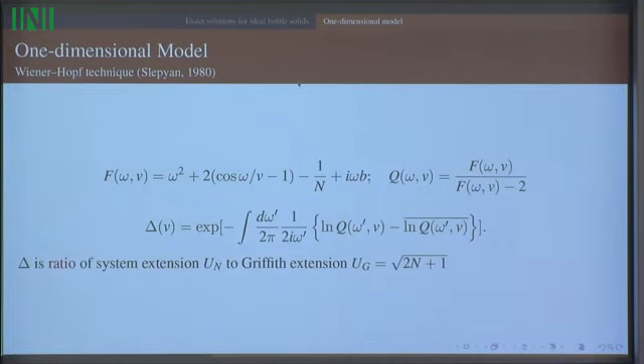So I measure extensions in units of that, and if I do that, then if I stick in a crack velocity v here and then just do an integral over this dummy variable omega prime, then I obtain how hard I have to stretch the system to get the crack to move that fast. So I find natural units. To measure extension, I stretch the system up, and then this says, the crack will run at this speed at that extension. And the harder you pull, the faster it runs. It's really not all that surprising.